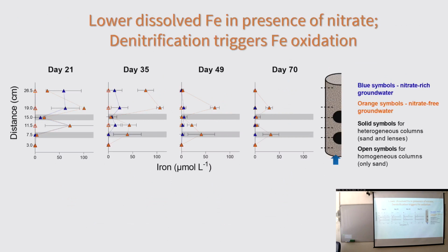And then when we looked at aqueous phase concentrations of iron, this being the reduced form of iron, so iron 2, we immediately saw that there was a clear influence of the nitrate presence. So here we can see that aqueous phase ferrous iron levels were consistently lower in the nitrate-rich groundwater. Okay, you can see here that the blue symbols, I think I said the opposite, the blue symbols are consistently lower than the orange ones, so we have lower iron concentrations in the presence of nitrate.